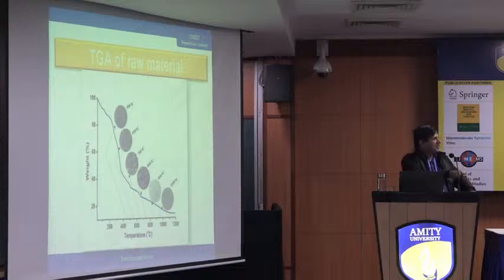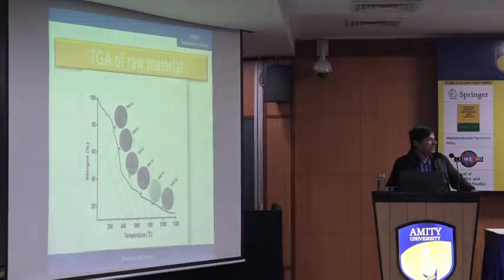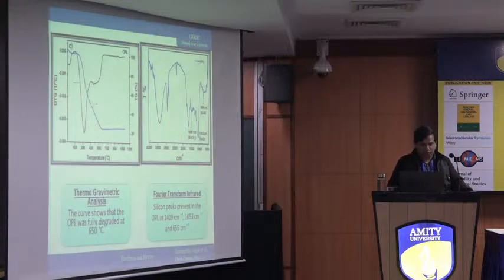Subjected this kind of precursor to thermal gravimetric analysis, you can see here weight loss is taking place, and from 400 or 500 onwards, you can see a spherical shape starts forming. When you increase the temperature, you will see that a very pronounced spherical shape nanoparticle has formed. So it's not only the nanoparticle synthesis, the temperature also plays a dominant role. You should know at what temperature to synthesize and how to control such kind of nanoparticle.